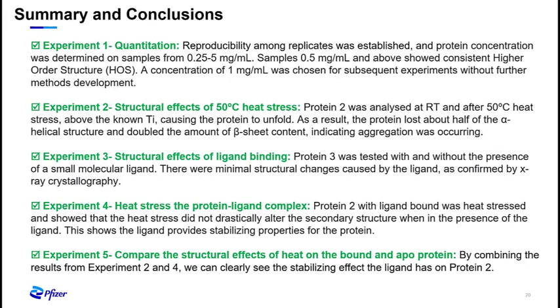In our second experiment, we looked at structural effects of 50 degrees centigrade heat stress. Protein 2 was analyzed at room temperature and 50 degrees, which is above the known TI, causing the protein to unfold. As a result, the protein lost about half of its alpha helicity and doubled in the amount of its beta sheet content, indicating aggregation was occurring.